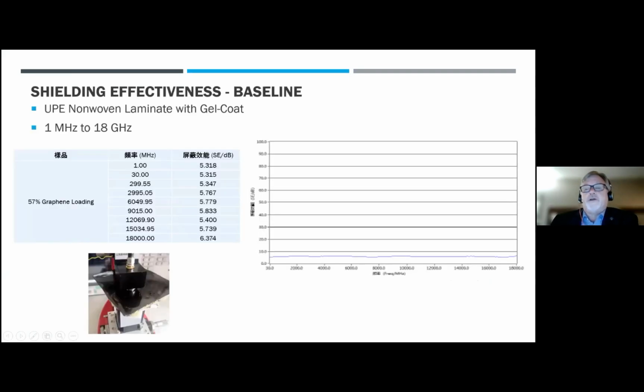So here's another instance of showing some technical data. We have a shielding effectiveness baseline that we're demonstrating here. This is an unsaturated polyester again, but this is a non-woven laminate. So it's got essentially fibers in there with also a gel coat on it. And you can see a picture of it in this slide here, where we are measuring the shielding effectiveness. And this was something that we had talked about in a previous slide.